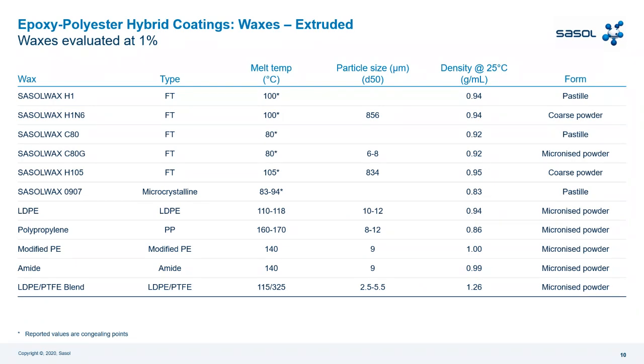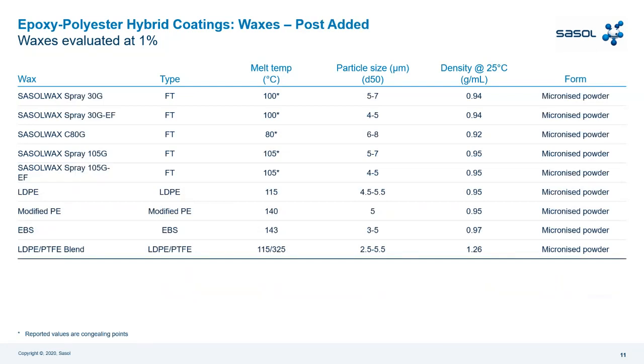Then we use from competitors LDPE wax, melting point 110-118, particle size 10-12, in micronized form, of course. Polypropylene wax, melting point 160-170, with particle size from 8 to 12, micronized. Modified PE, melting point 140, particle size 9 micron. Amide wax, melting point 140, 9 micron as well, micronized. And a blend of PE wax and PTFE fluoropolymer, with melting point 115 the PE and 325 the PTFE, particle size 2.5 the PE wax and 5.5 the PTFE, always in micronized powder. This is for extrusion. Post-added, so post-extrusion, we use only micronized powder.